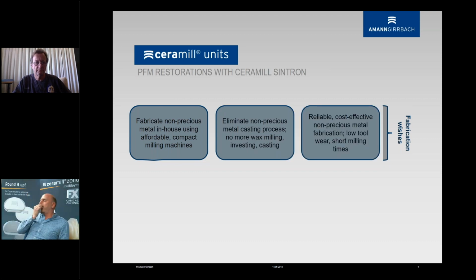But basically it is more uniform than anything cast, just because your sintering and the process of the production is very different from when you're casting it and potentially overheating it and changing the whole alloy. All those composition-wise fine-tuned elements in there, they all go out the door if it's being overheated and treated differently than it should be, and it's difficult to judge that with any way of casting, no matter induction or open flame.